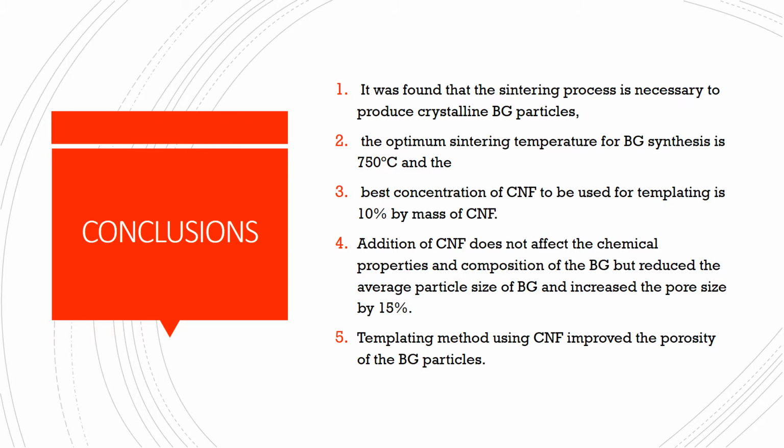The addition of CNF does not affect the chemical properties and composition of the bioactive glass, but reduces the average particle size of bioactive glass and increases the pore size by 15%. The templating method using CNF improves the porosity of the bioactive glass particles.